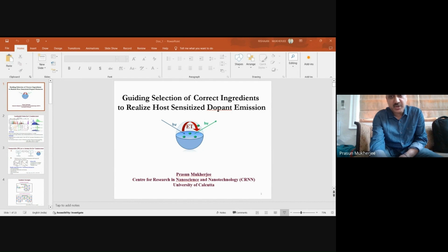an appropriate semiconductor nanoparticle matrix, where the nanoparticle can act as an optical antenna, that is, a sensitizer, as well as a protector matrix. We can see from these lifetime measurements that in bulk solvent the lifetime is much faster, only around 4.8 microseconds, whereas in the nanoparticle the emission is significantly lengthened.